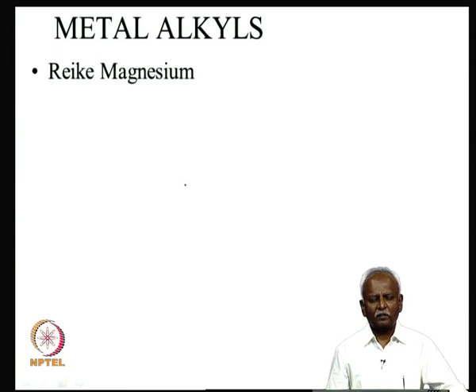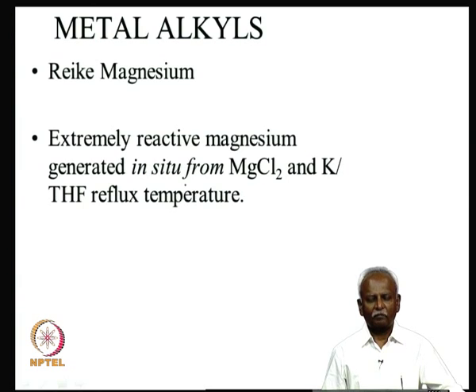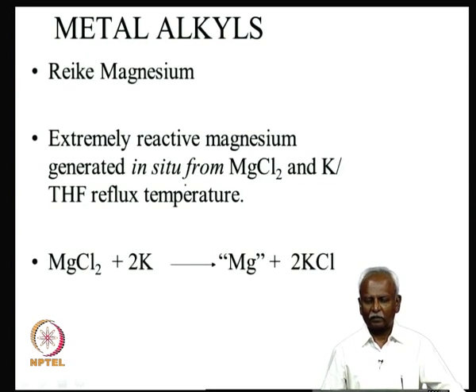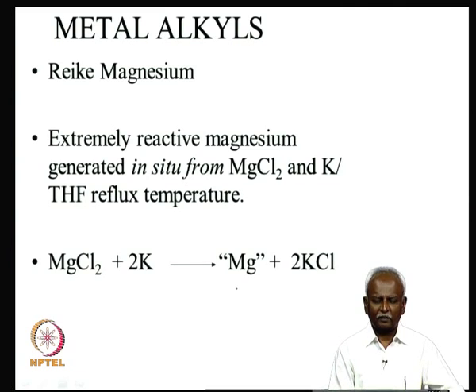So it was discovered by Rieke that the magnesium, which is usually used as a powder or as a metal ribbon, can be activated further by a special process. This very reactive magnesium is generated in situ by reducing the magnesium chloride with potassium in THF. At the reflux temperature of THF, potassium melts and forms a metal globule, and that metal globule reduces the magnesium chloride and forms a black magnesium powder. This black magnesium powder is extremely reactive.